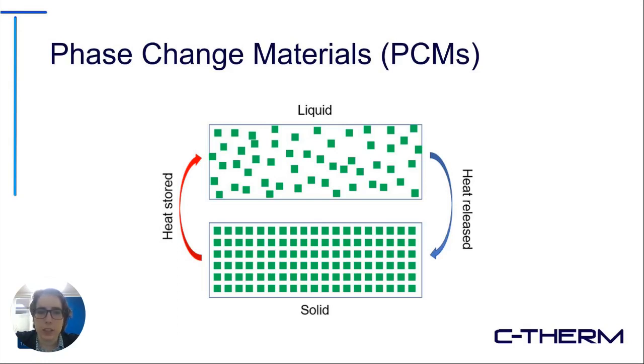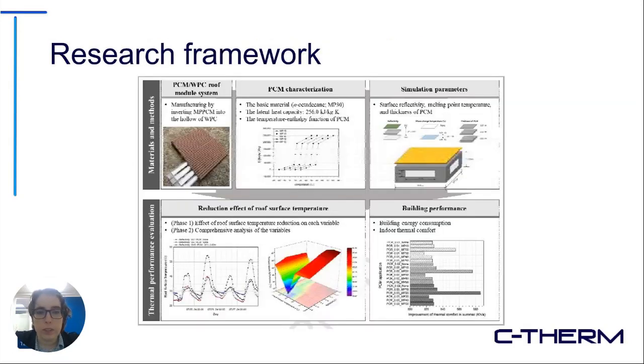These kinds of materials can cycle many, many times, although some of them, especially the newer, more bio-based ones, can sometimes degrade over time. The classical petroleum-based PCMs, on the other hand, tend to be very stable even across many thousands of cycles. So the framework of this particular paper started with designing the module system that included the phase change materials, and characterizing the thermal properties, including the latent heat capacity and the sensible heat capacity of the PCMs. They inputted the data into a simulation to determine how it would perform as a function of yearly temperature variations, both day-to-day temperature variations, as well as more broadly seasonal variations.